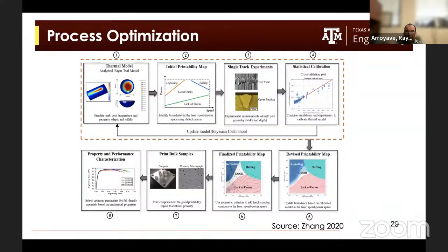So on the process optimization side, we have used a combination of physics-based models, machine learning, and experiments to come up with a framework that enables us to find optimal regions in the processing space that lead to parts that have low porosity, right? The first thing, if you're trying to fabricate something with additive manufacturing, the least you can do is to make sure that whatever you print doesn't have macroscopic porosity that would ultimately compromise the performance of the part, right? Pores lead to failure, such as fatigue, etc.